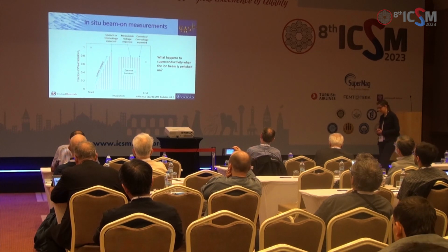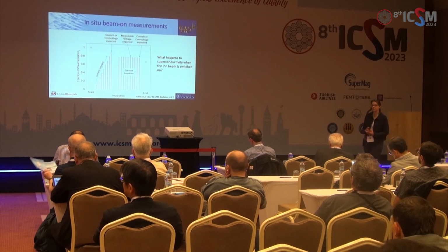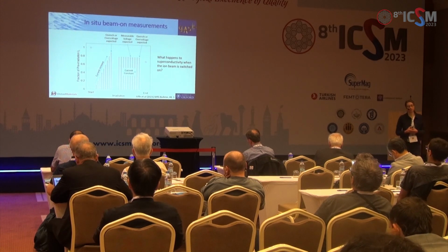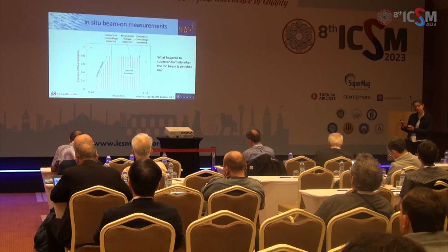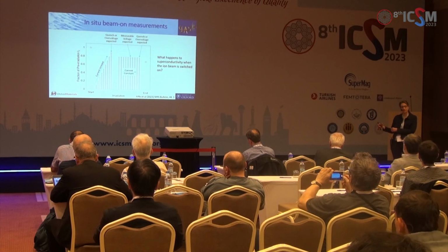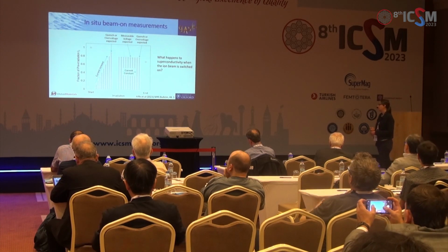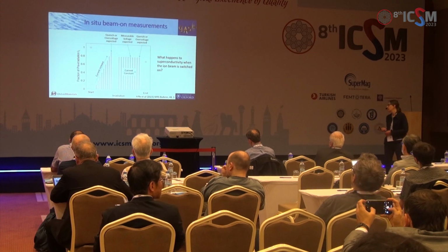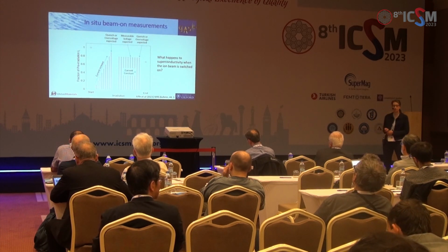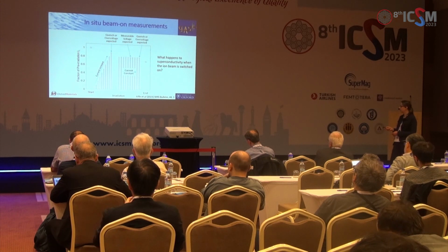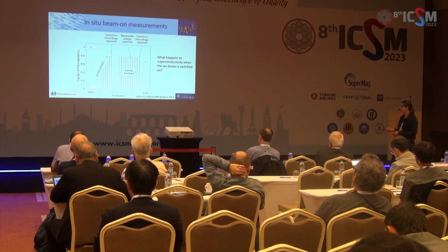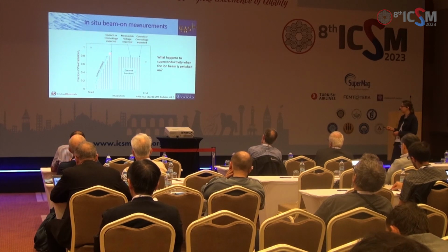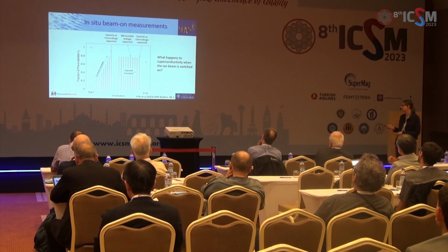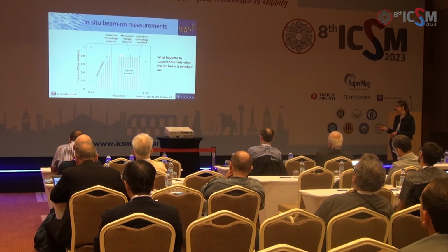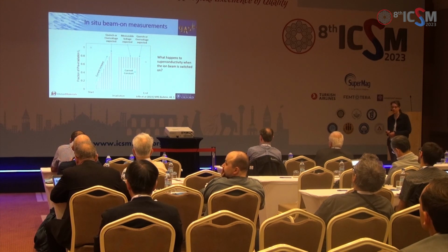Okay, so the final thing I want to tell you about is some recent experiments we've done with the beam on. So the experiments I showed before were we irradiated them cold, and then we turned the beam off and we measured JC with the beam off. We do these with pulse measurements, but we can also try to do the measurements with the beam actually on. And the measurement's slightly different. What we did was with the beam on, we started ramping up our current pulses in magnitude until we started seeing a voltage, some instability in the voltage. And then we backed off a little bit and did a whole series of pulses at the same magnitude of current.